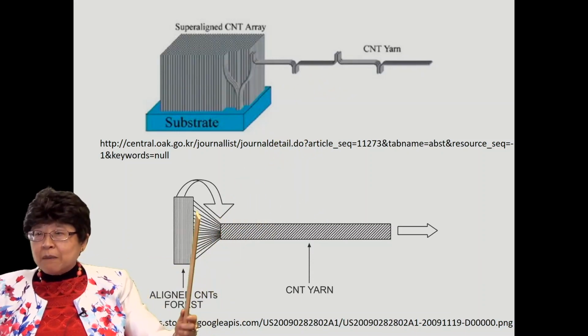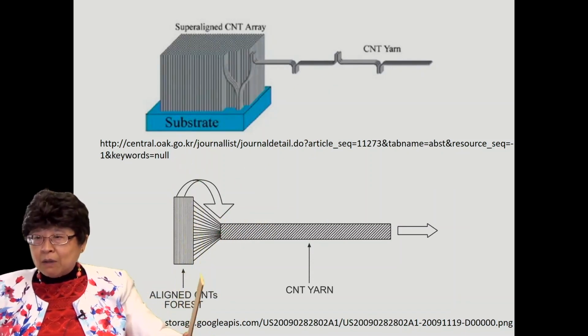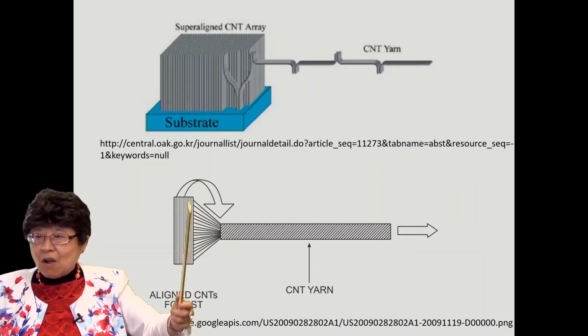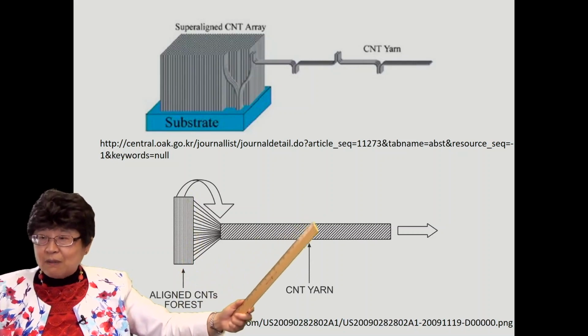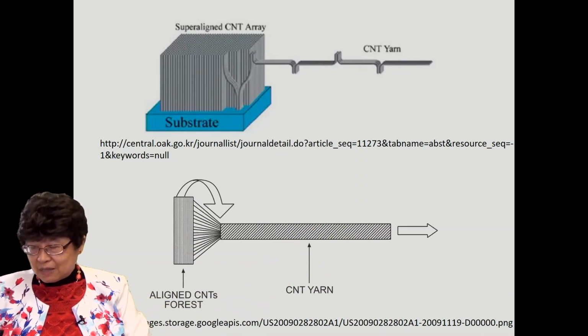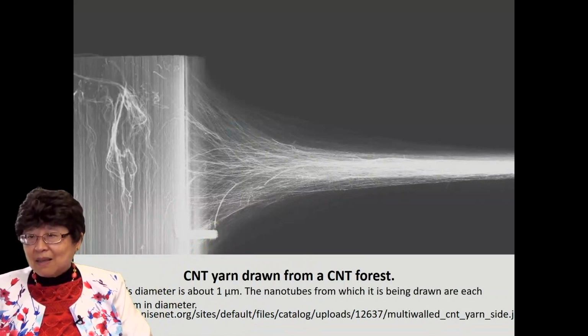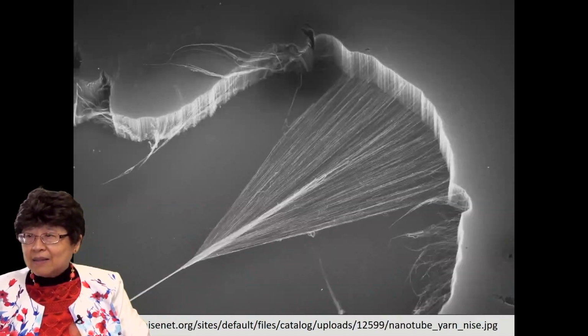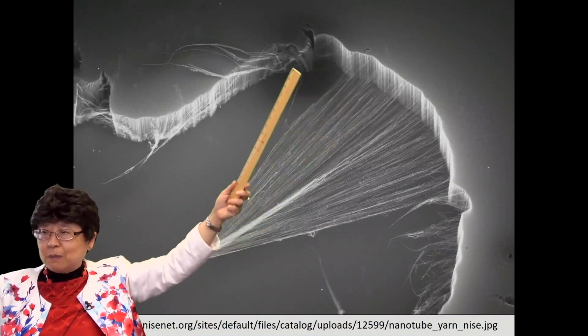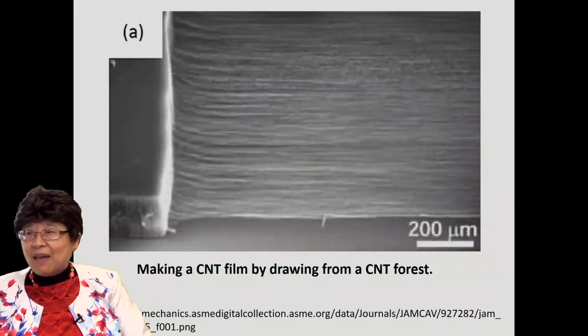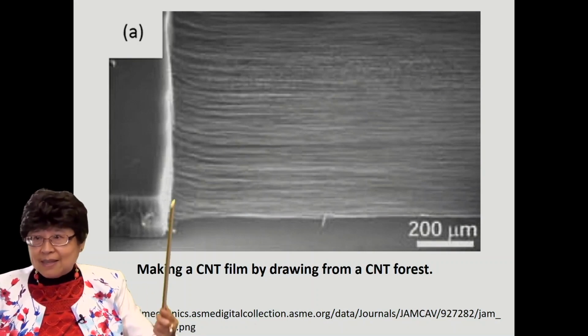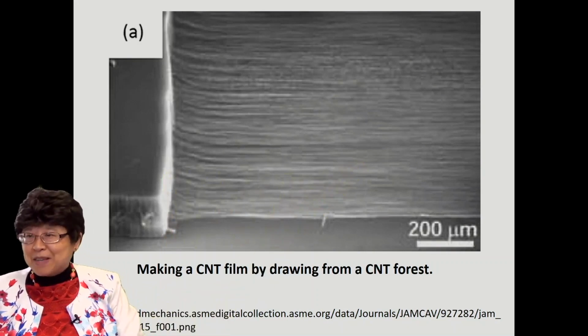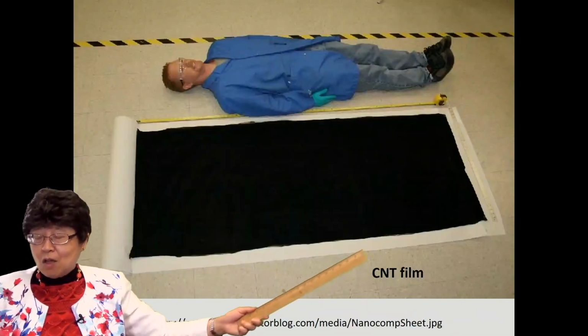And you can pull it not at one spot, but in multiple spots. So you have multiple yarns coming out, and then you twist the stuff, and you get a twisted yarn out of it. And this is a real image of the yarn that's drawn. You draw it from different points, and then you twist it together. And you don't have to twist, you can just lay them parallel, and it becomes a carbon nanotube film, and you can have such a long film.